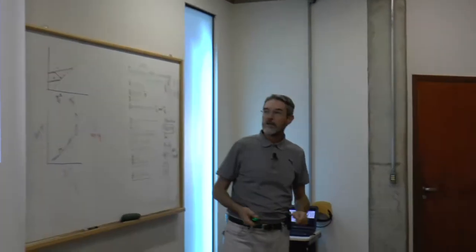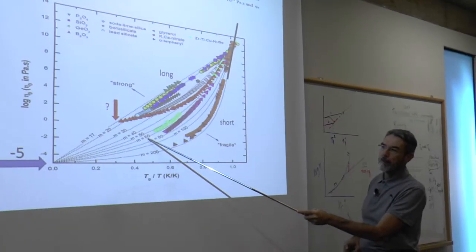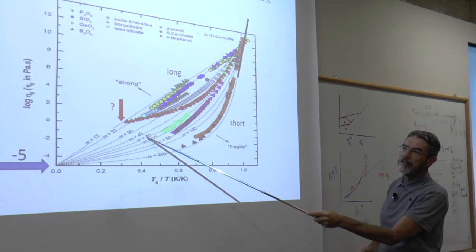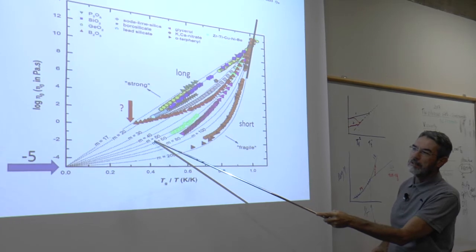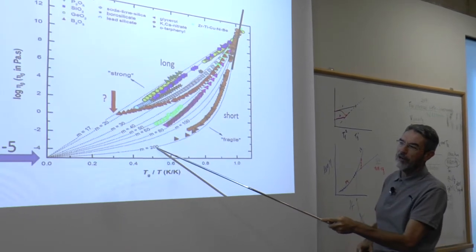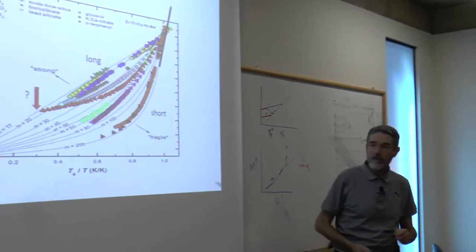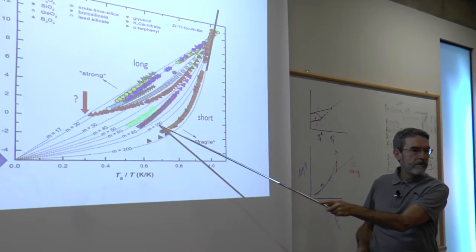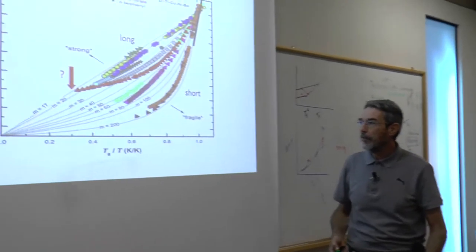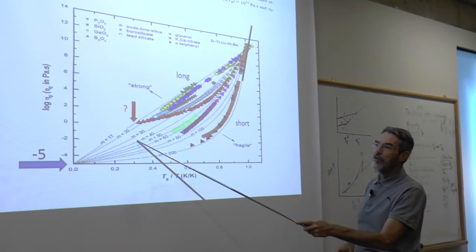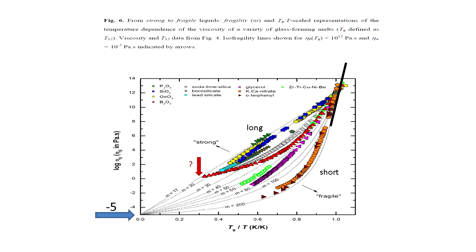Diopside, Paulo, that you work with diopside, the fragility of diopside is about 60. The fragility of lithium disilicate is about 45, will be here. And so on. Polymer glasses have very low fragility. Oxide glasses, the maximum I have ever seen is about 100. Up to 100 for oxide glasses. Metallic glasses also tend to be fragile, and the fragilities go from 40 to 80 or so, more or less, right?